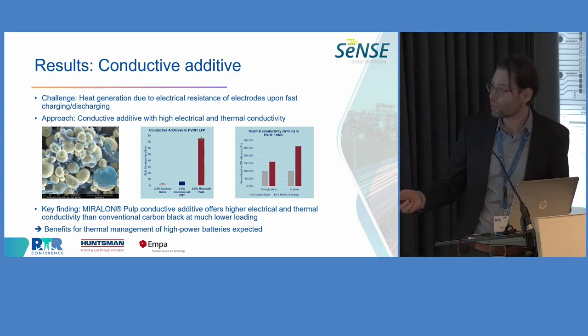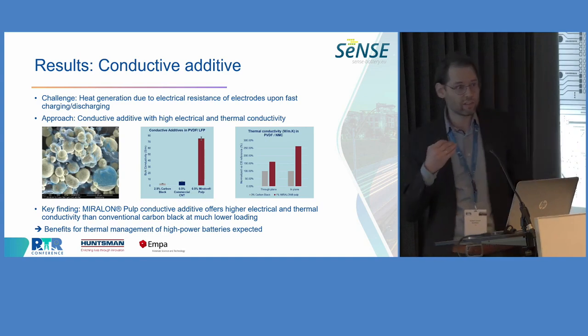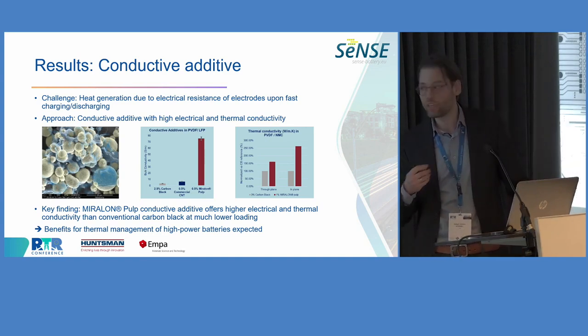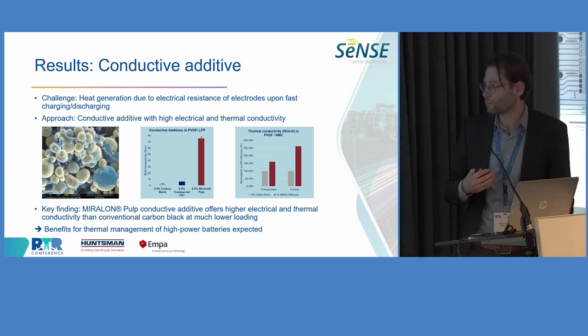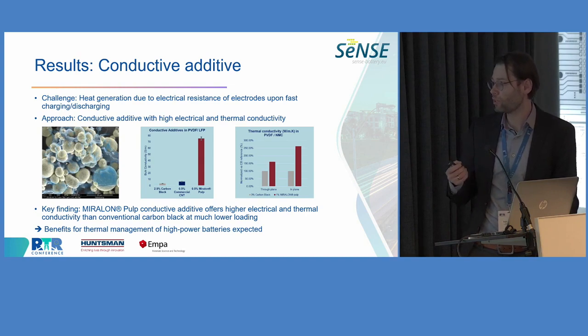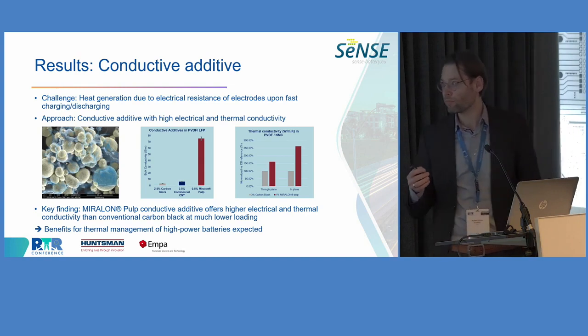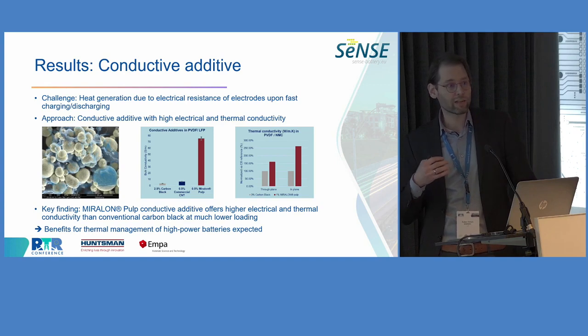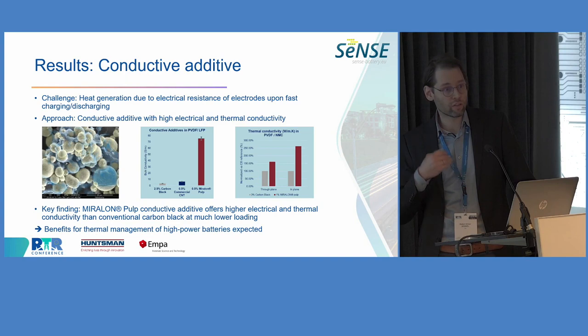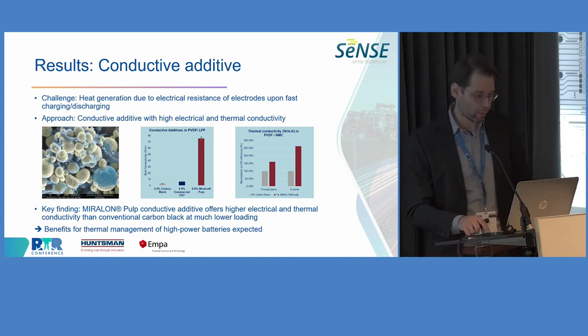It has a quite interesting morphology. It's a CNT-like, so carbon nanotube-like, material that wraps itself around the active material particles. And we are at the moment investigating how the use of this conductive additive benefits the thermal properties on the cell and even pack level.